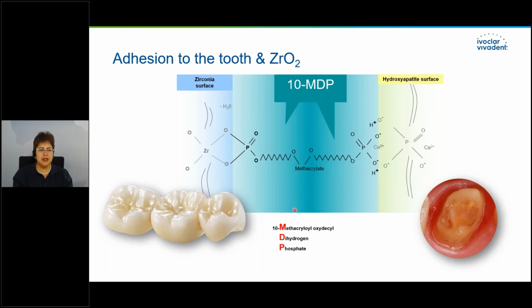10-MDP. This 10-methacryloyloxydecyl dihydrogen phosphate stands for this 10, and the MDP is included as a primer for zirconia, because of its reaction with the zirconia surface, and this is the reason why we don't need an additional primer. And the phosphate group will bond to zirconia or any metal restoration, aluminum oxide or metal oxide.